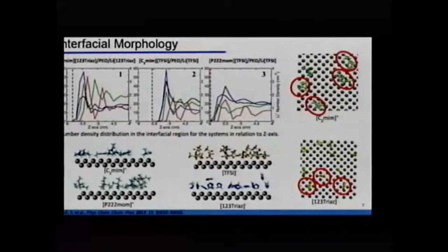And also, this random or broader layer here also influences the distribution of PEO close to the surface. If we look at the two systems that we have with imidazolium, we see sharp peaks from PEO close to the surface and higher densities than in the bulk. But here, when we have phosphonium, we don't see much difference between the bulk and the interface region.